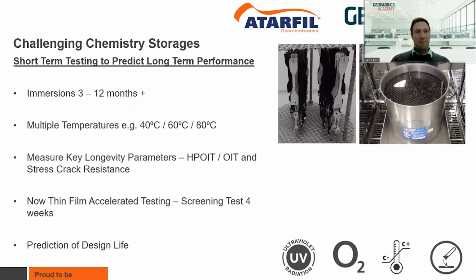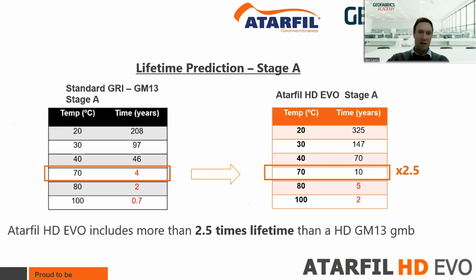In terms of the testing, I touched on this earlier. We can do immersions for 3 to 12 months with HDPE and predict long-term performance. We basically immerse it in different temperatures, 40, 60, and 80 degrees, to try and accelerate that process. And it's really there to compare these performance criteria, which I touched on: HPOIT, stress crack resistance, and assessing how those perform after exposure. So I won't dig into that again.